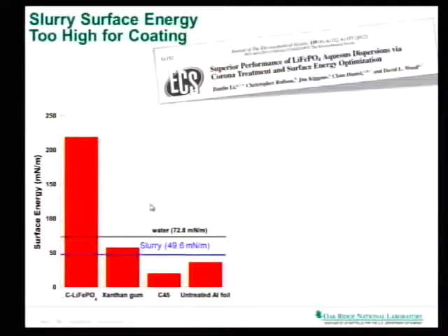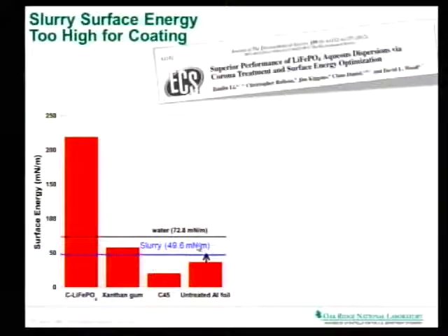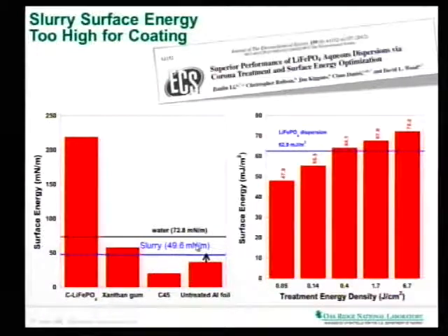So if we have all of our material in the slurry, it gets a little better, but nowhere close enough to where we can actually meet these values. So we need to close this gap somehow. So what we did is we looked at plasma treating surfaces. What an atmospheric plasma gives you when you run it over a surface is that it allows you to clean the surface. It takes a lot of the, I call it goo, off, anything which floats around in the air and settles on it. You can also controllably oxidize your surface, and you can really dial in the surface energy you need.